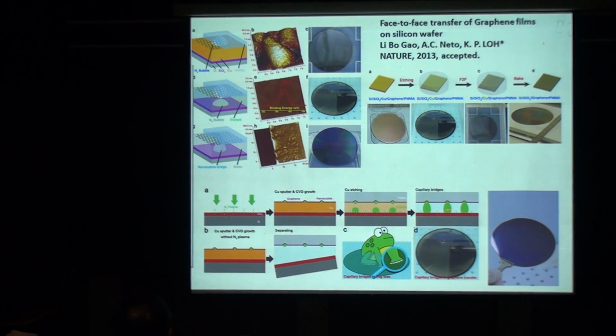Although there's water in between the graphene and the substrate, the graphene does not delaminate. It still remains attached because of these bubbles holding the thing together. This is the capillary bridge. And subsequently, when you undergo a baking, then the graphene will just stick onto the wafer. So this allows us a very good way. We call this the face-to-face transfer of graphene film, and because this is a technological breakthrough, it has been published in Nature.